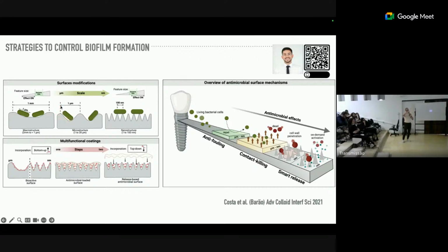We might increase the total surface area, but the active surface area is being reduced, especially in the nanostructure. As you can see here, we have a very high area, but the active area for the bacteria to adhere is very low. So we have in the literature several nanostructure surfaces that can repel the bacteria by themselves without having any antimicrobial.